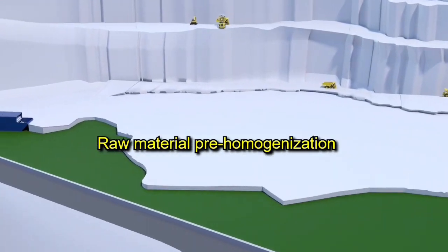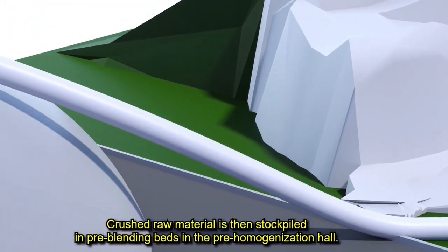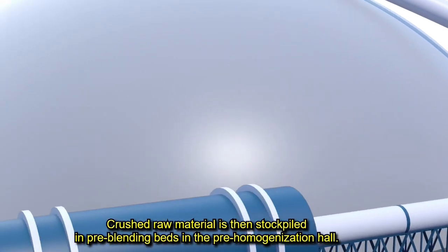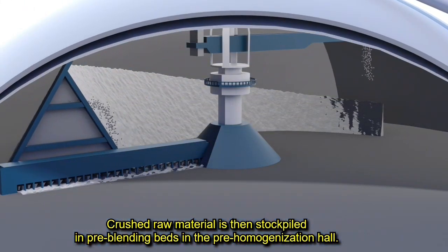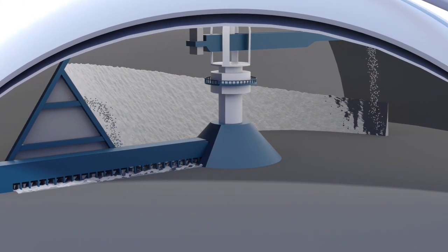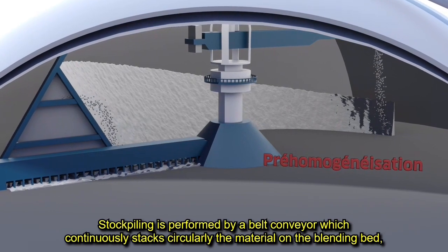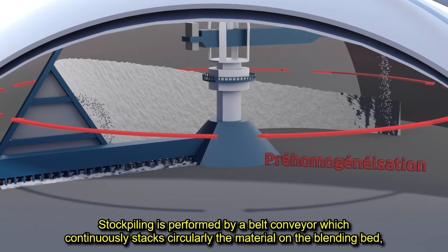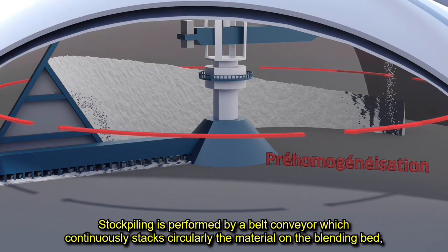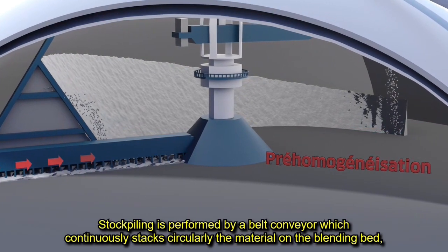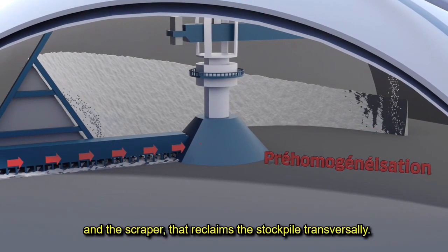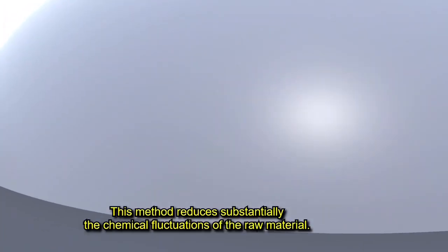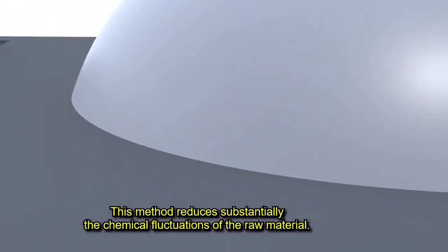Raw material prehomogenization. Crushed raw material is then stockpiled in pre-blending beds in the prehomogenization hall. The circular stockpiling is performed by a belt conveyor, which continuously stacks circularly the material on the blending bed, and a scraper that reclaims the stockpile transversely. This method reduces substantially the chemical fluctuation of the raw material.